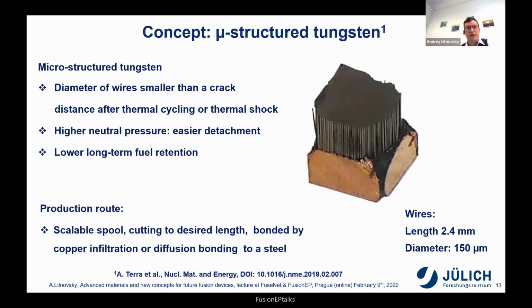There will be another example of how you may do this, but let's look at another concept for the divertor, for this 10 to 20 megawatt. It is similar in the sense that we are using mostly the same fibers, not in a matrix, but put as a material. It is so-called microstructured tungsten. So there are a series of fibers with the same dimensions, 0.15 millimeter diameter, cast and molded on the copper via infiltration or diffusion bonding on the steel.